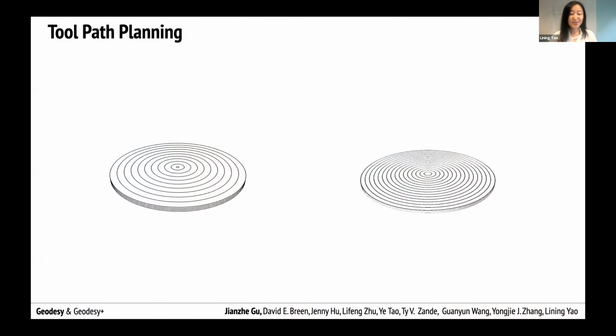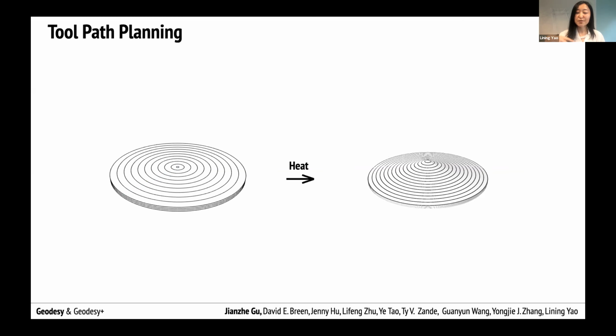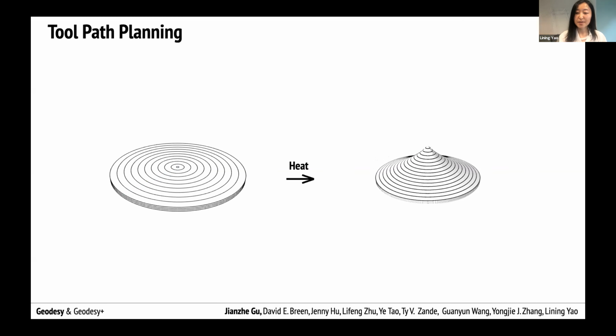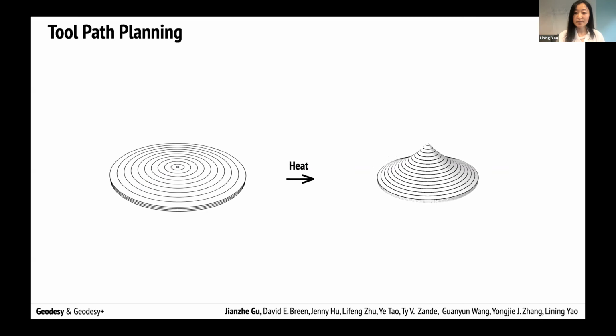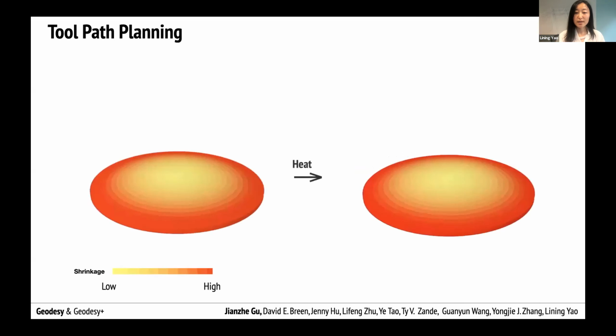So the very simple assumption is that if you just print continuous lines, the shrinkage will only happen along the printing direction, and there is almost no shrinkage perpendicular to the printing direction. And then again, if you print a disk with this continuous curve, and if you heat it up, it will morph into a dome, in this case, a cone.